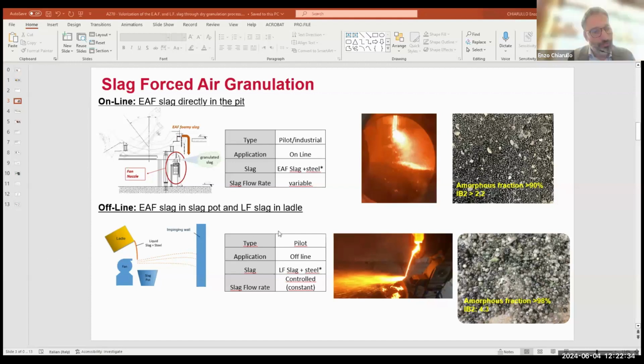The second methodology is the offline EAF slag. In this case, the ladle is taken to the slag granulation station, where the liquid flow is hit by the airflow for the slag granulation process. In this case, the ladle is on a crane. We are developing a tilter, a tilting mechanism that moves this kind of ladle. This is the material obtained. This is ladle furnace slag that has a silica content of around 20%. For this reason, we obtain this kind of green material.